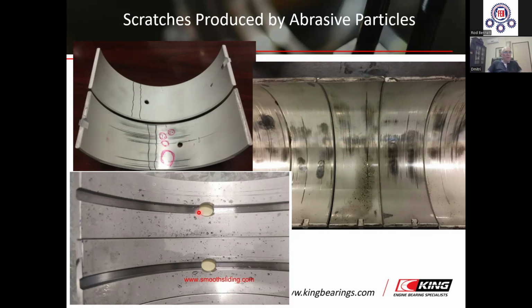And pay attention to this image. You see the abrasive particles embedded into the bearing surface. When they are embedded into the surface, they are neutralized, but of course, the bearing cannot neutralize all abrasive particles in the oil.